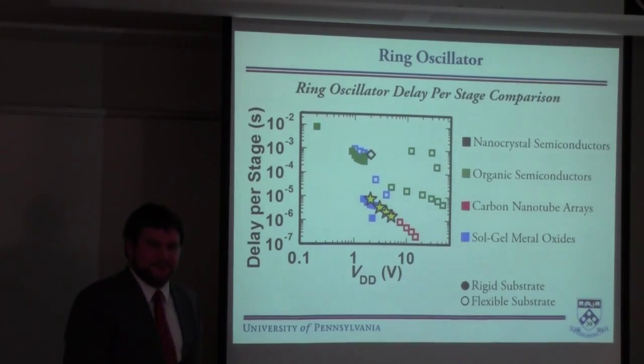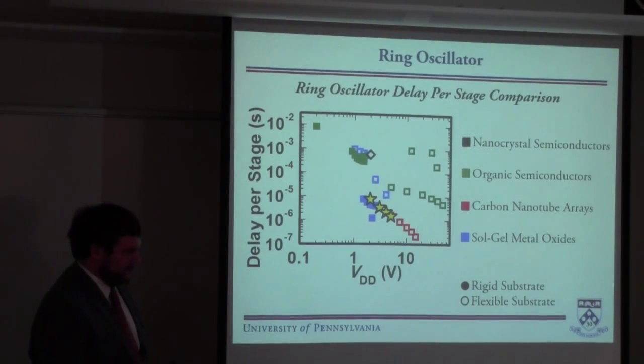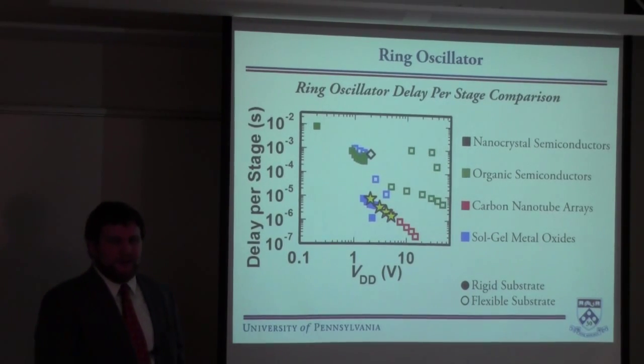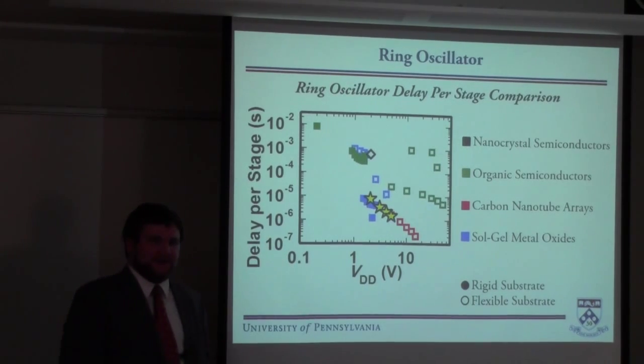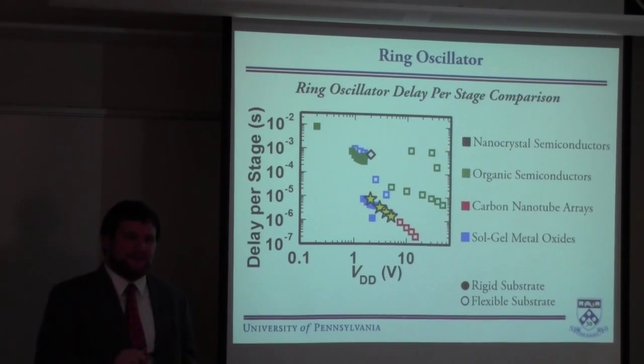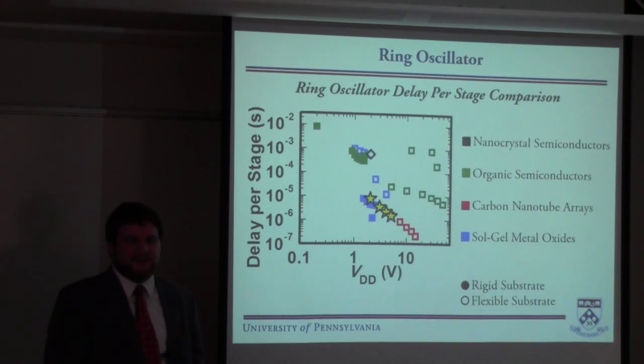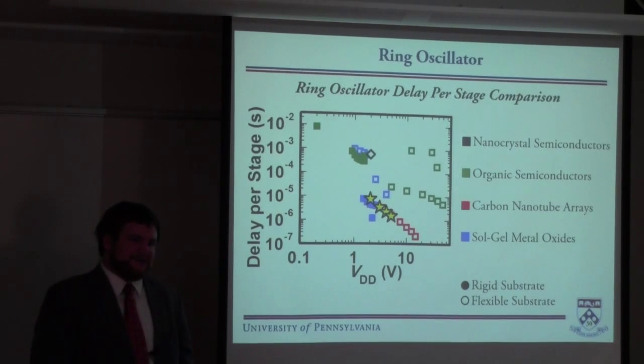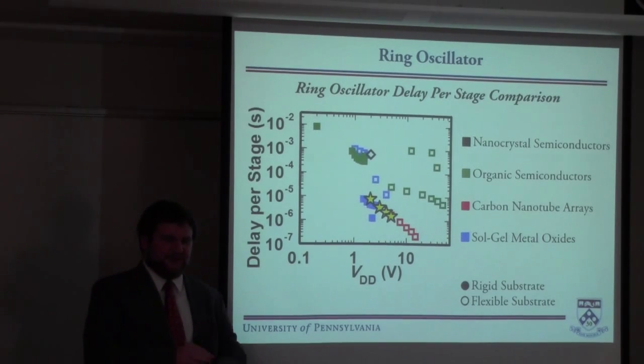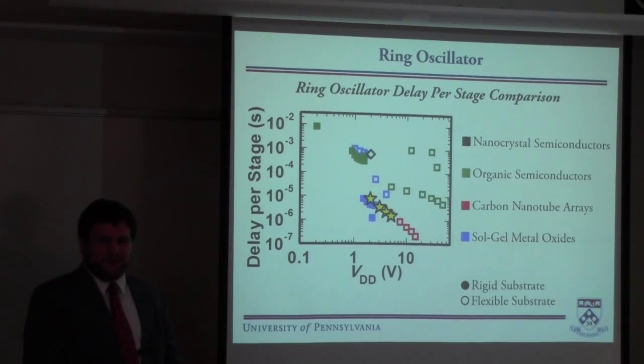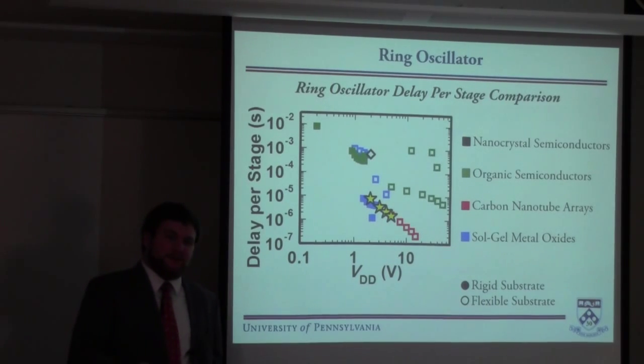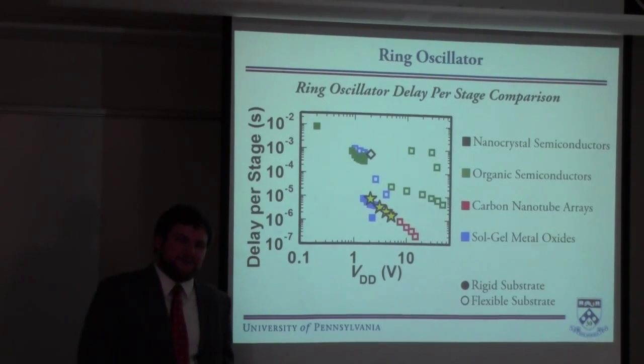Well, one of them is threshold voltage. These devices had a threshold voltage of around 1 volt. That's one of the biggest limiting factors of all this. You can squeeze your threshold voltage down by making your oxide layer thinner and thinner, but we're already working at like a 15 to 20 nanometer oxide and seeing some leakage. So that's one of the biggest difficulties, just the thickness of the oxide, because in a lot of these processes, not everything is completely smooth. So you have to keep your oxide reasonably thick to keep it from leaking and still being able to form over all the features. Okay.